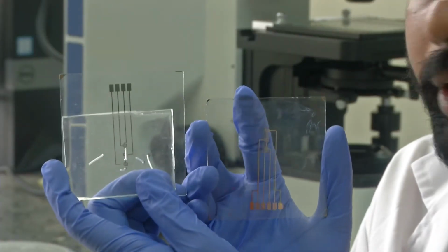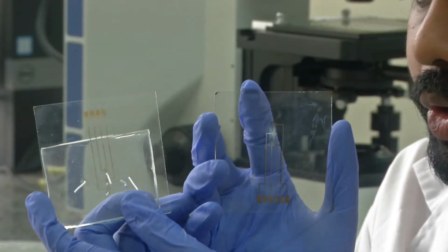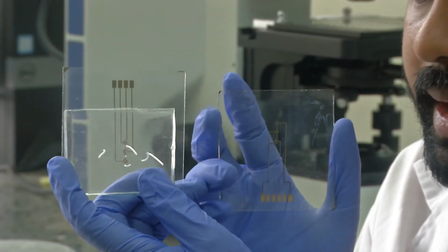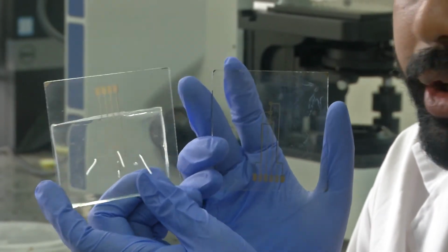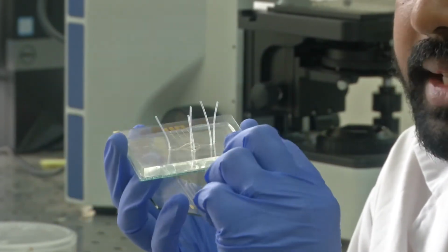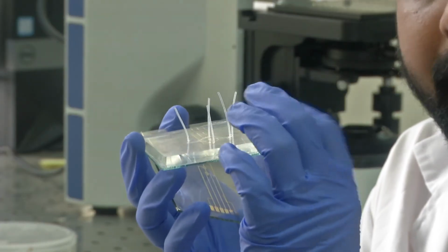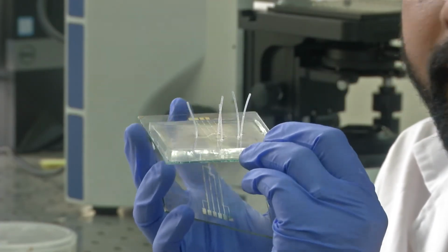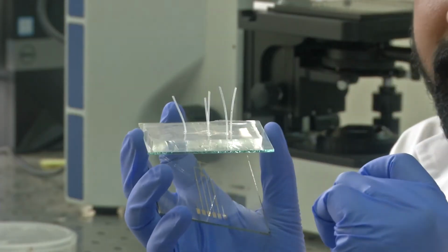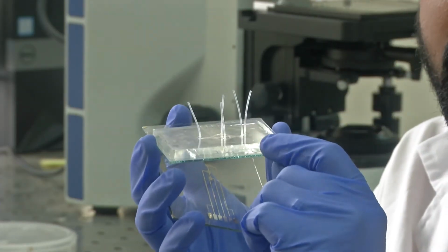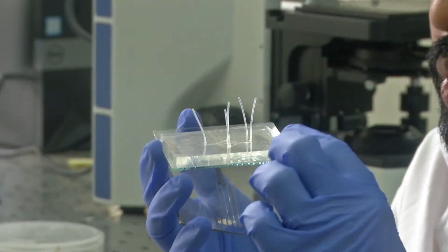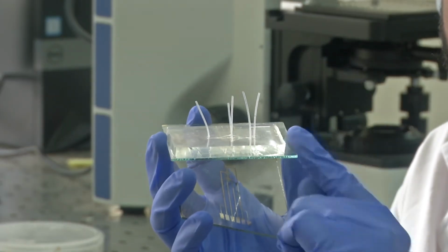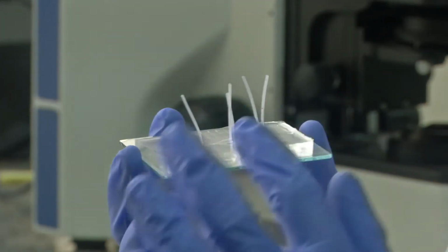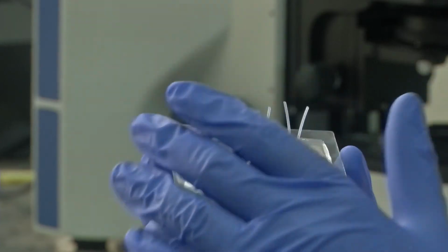So this is the microfluidic device that you already saw in the previous module, correct? The PDMS membrane was there, and you had a glass slide. I forgot to tell one thing: the glass slide is bonded to this PDMS membrane through oxygen plasma bonding. We have seen the oxygen plasma system in the lab. You activate both surfaces with oxygen plasma and then you put them together, and they will bond. That is another process.